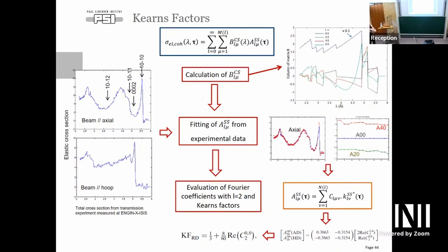And so by default, you've got something like a fiber texture. Exactly. Yeah. But you don't care, basically, right? The scale factor will average everything. Might not actually be fiber, but it doesn't matter, right? Exactly, it doesn't matter. But the main thing here is that for this particular symmetry, you have just two components that you need to see. Yeah. And that's perfect, because we have only two orientations. You don't have to measure tons of orientations for this particular value.